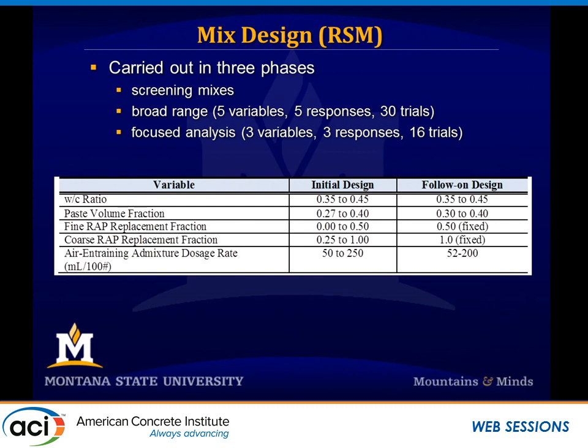So it was carried out in 3 phases. We ran some screening mixes to get some general idea of the ranges of the variables and what responses were important and what variables were important. Then we did a broad range, so we did a response surface methodology over a big, wide range of variables, and in this case, 5 variables and 5 responses, and it resulted in 30 trial mixes, right? We ran through those 30 trial mixes, and we had a few issues with it. Mainly, it was just off-center a little bit. We were targeting a certain area, and we were off a little bit, and so when it came to optimization, it didn't work out the way that we wanted to, so we did a more focused analysis where we narrowed our scope and redirected, which was 3 variables and 3 responses, and that one worked out really well. Okay, and I'll talk to you a little bit more about some of those results.